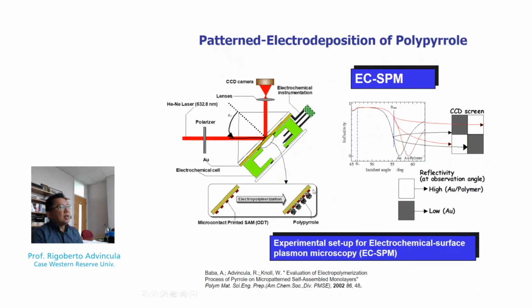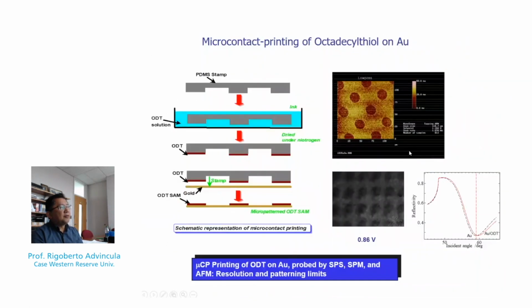And then finally, we eventually have a polymerized polypyrrole on that pattern as shown here. So electrochemistry allowed us to investigate the redox behavior. In situ, the deposition of the polymer produces a shift to higher angles of that reflectivity curve. But again, AFM is a very important tool for us to combine with.